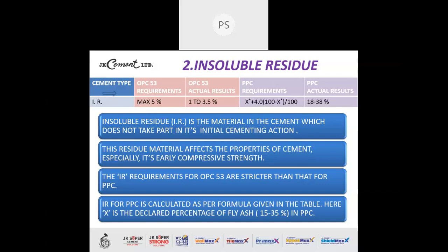Now, what is insoluble residue? Insoluble residue is the material in the cement which does not take part in its initial cementing action. This residue material affects the properties of cement early compressive strength. As we look at the strength, as I mentioned earlier, the 1 day, 3 day, and 7 day strength of PPC is very low in comparison to OPC, and this is the reason why insoluble residue is very high in PPC, and that is why it lags in the 1 day, 3 day,